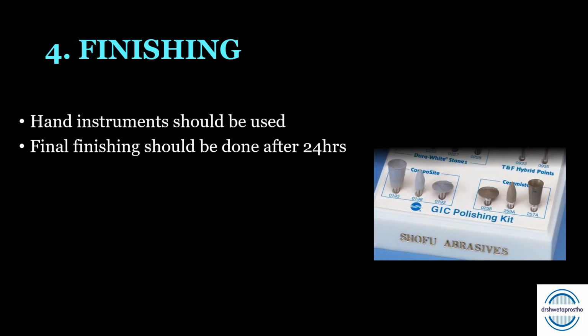Next is the surface finishing. After removal of the excess material, we will use the hand instruments to do the initial finishing. We will not use the rotary tools because they can cause ditching. And the final finishing should be done after 24 hours.